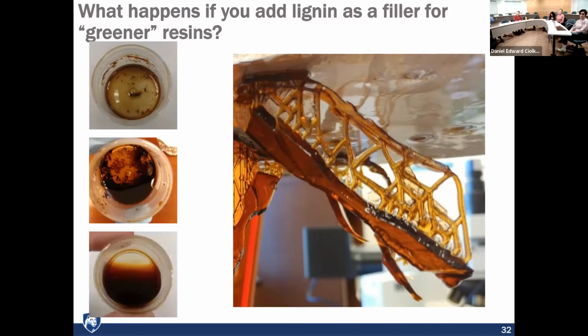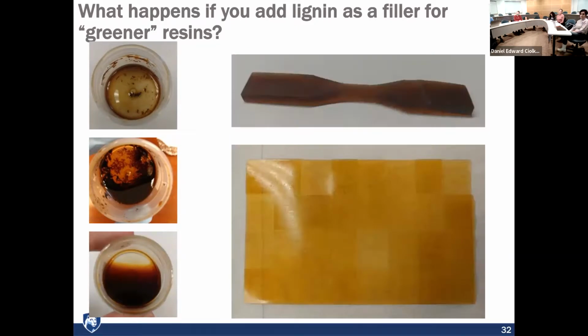And so we can make homogeneous resins like this if we do some chemistry. And when we do that, we get nice specimens that look like this one. This is actually what we call a tensile testing dog bone. It allows us to test the mechanical properties of the resins that we make. And this is a window pane test. This is how we test for that critical cure energy and that penetration depth. So once we homogenize our resins with some chemistry, we get these nice objects that we can print, and they are brown.